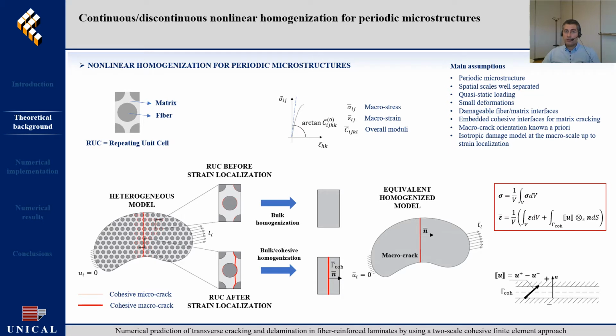The proposed continuous-discontinuous nonlinear homogenization is performed on a properly identified repeating unit cell, which is representative of the assumed periodic composite microstructure. The other hypotheses of this model are perfect separation between micro and macro scales, quasi-static loading conditions, small deformations, damageable fiber-matrix interfaces, and breakable matrix, modeled as a collection of cohesive elements embedded in a continuous phase.